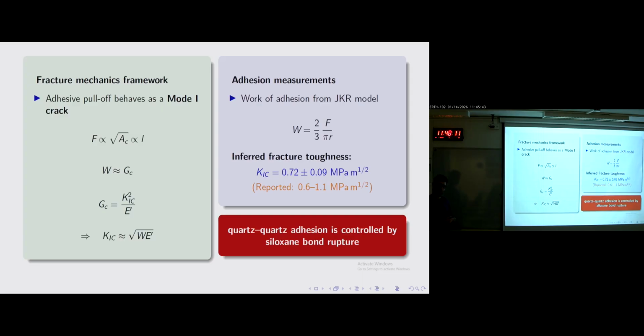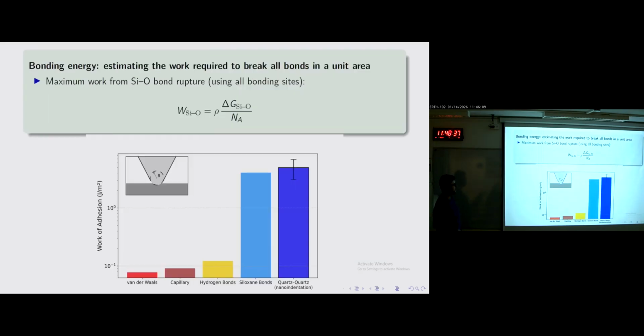And when we propagate a crack, when we open up a crack in quartz, we inherently break silicon-oxygen bonds. So this is the first reason to start believing that the adhesion that we see from nanoindentation tests is coming from breaking and rupturing silicon-oxygen bonds. Okay, let's get some more.